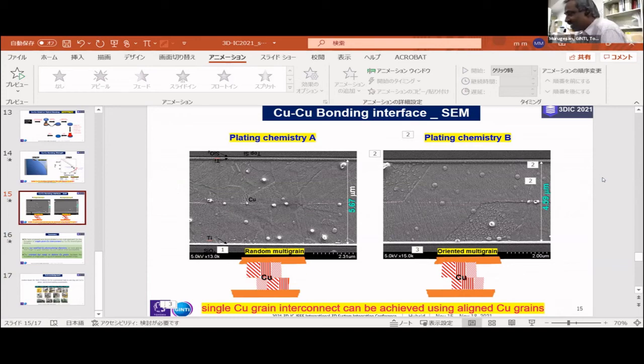Yes. And is there any specialty or any requirement for the grain orientation, such as 111, 110, or 100? I think if you go for 111, obviously the mechanical property will be very, very nice, no doubt. But the question is, the moment you go to 111, your grains may not always align 111, because the grain size is very small when you go for 111. Unless you prepare a 111 epitaxial film, that's a different story. But during electroplating, you will never get an epitaxial film. It is always polycrystalline, randomly oriented.